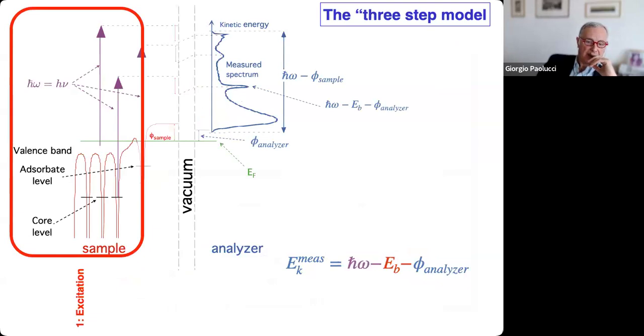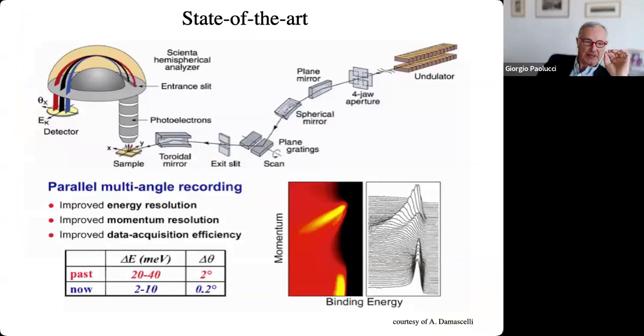Now we go and study what the three-step model is. But just before we do that, I just want to stress that by measuring the angle of emission of the electrons, you can get information on the band structure of the sample. I hope many of you know what the band structure of a solid is. And you measure basically occupied states. That's different from, for example, absorption spectroscopy, which was mentioned before, where you get a combination of initial and final states, so you have to decouple the information from the two states. In this case, since we are extracting the electrons all the way away from the sample, the main information is coming from the initial state, which are the occupied states.